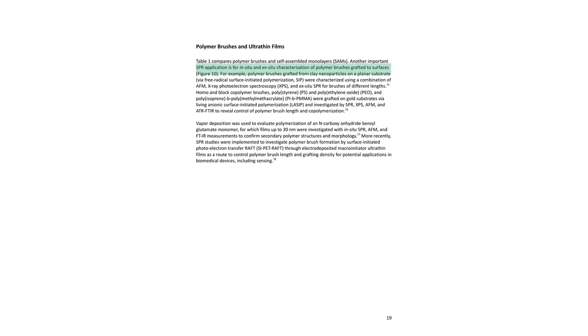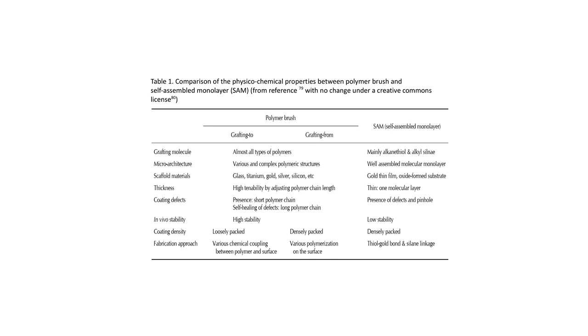Another major area of their research involves polymer brushes. Unlike a simple flat film, polymer brushes are made of polymer chains that are tethered at one end to a surface, often at high density, causing them to stretch away from the surface like the bristles of a brush. These structures are distinct from self-assembled monolayers, or SAMs, which are typically just a single molecule thick. Polymer brushes can be made from a wide variety of polymers. Their thickness can be tuned, and they can have more complex architectures.